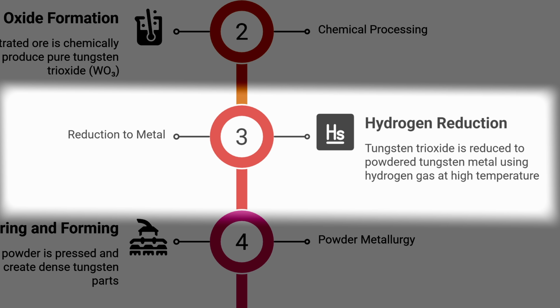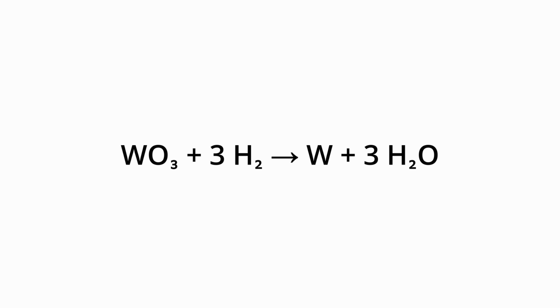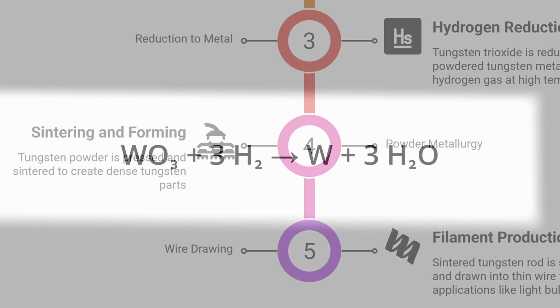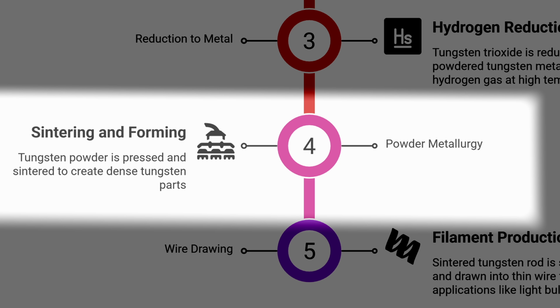So now we have tungsten in oxide form and we need to reduce it to metallic tungsten. This is typically done by reduction with hydrogen gas in a high temperature furnace. The tungsten trioxide powder is heated in a stream of hydrogen, which chemically strips away the oxygen. Now the reaction looks something like this, and the end product is powdered tungsten metal and water vapor that escapes. Sometimes carbon, coke, is used as a reducing agent instead, though hydrogen is cleaner and yields higher purity metal.